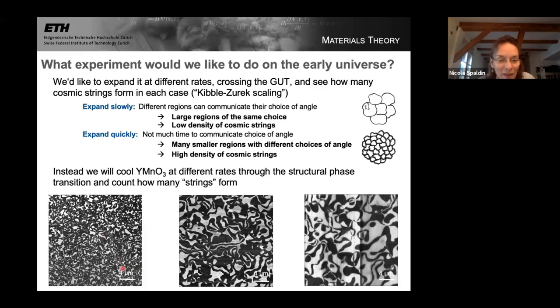This is the same scale bar, and you can see there's really a measurably different number of the topological defects in each case. So then one has a bachelor student go and count how many defect intersections one has in each case, and one can really measure the number of defects that form as a function of the cooling rate.